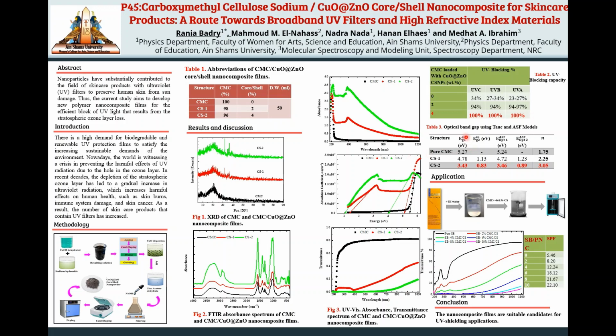Additionally, we calculated the optical band gap using 2 models, the Tauc equation and the absorption spectra fitting model, and we found that the band gap decreased with increasing core shell nanoparticles concentration, and the 2 models are consistent with each other. Additionally, we calculated the refractive index, and it was found that it increased to twice its value with the addition of 4 weight percentage of core shell nanoparticles.